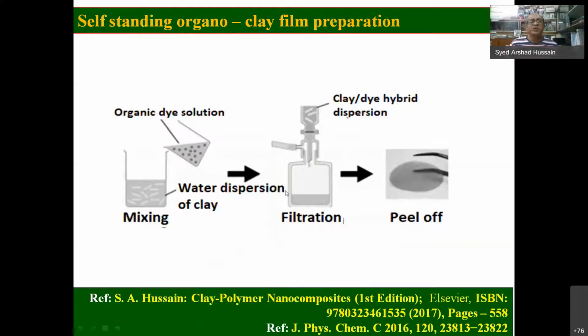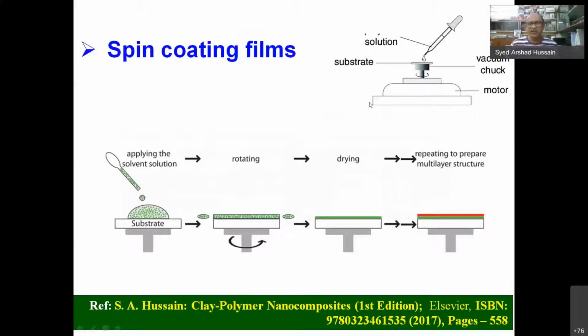And here we prepare self-standing films. We prepare a mixture of the clay and organic systems, do ultrasonication, and then we have a suction system. We use some membrane here, sometimes a cellulose membrane of a fraction of a micron pore size. Then we put the mixture here, we suck with a vacuum pump, then a film forms on the membrane, and we can peel off the film from the membrane. It's self-standing.